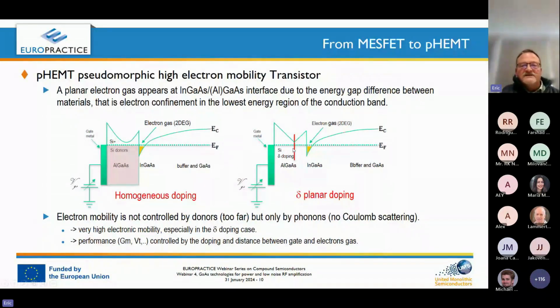You can see here, the doping is planar, so the silicon are deposited on this plane. And this is very interesting because it's a way to separate strongly the carriers here to the donors, to the electron donors here. And through this separation, there is no Coulomb scattering in the structure, which means the electron mobility is no more controlled by the Coulomb scattering, but is controlled by interaction with phonon in the structure. And this gives a very high electron mobility, especially so in the case of delta doping, because here, in the case of homogeneous doping, you may have still a small interaction between the electron gas and the donors.